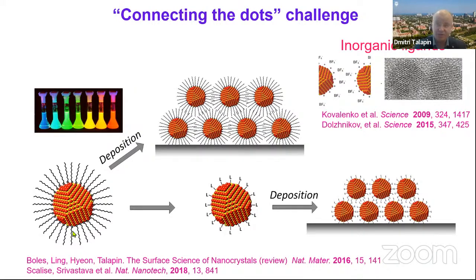Because if you have at the surface a layer of electrically insulating ligands, they will form a bilayer that will introduce insulating barriers between individual particles. And electronic states will not be able to delocalize. So they will be strongly localized on individual building blocks, and our imaginary sodium chloride will be a linear combination of sodium and chlorine. So there will be no new states developing. And that's a big challenge. And we spent about 10 years working along these lines to solve it.